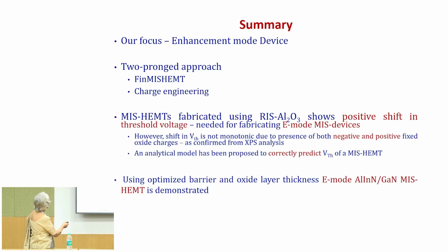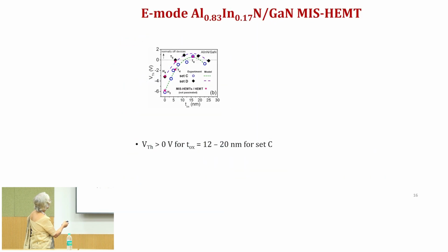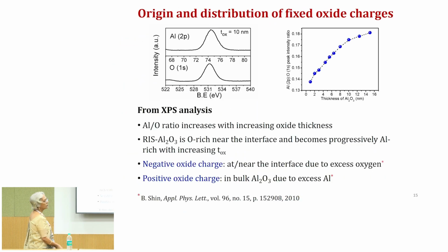So, my question was in the energy space. Are these mid-gap charges or are these mobile charges? These are not mobile charges, these are fixed charges. They are because of oxygen interstitials. It's oxygen rich aluminum oxide. So, there are oxygen interstitials and they are not able to move. So, it's fixed charge. And how deep or shallow are they in the energy space?